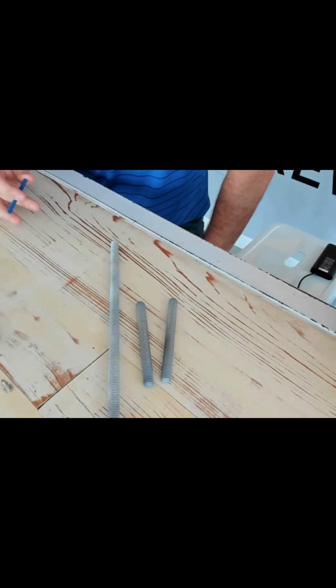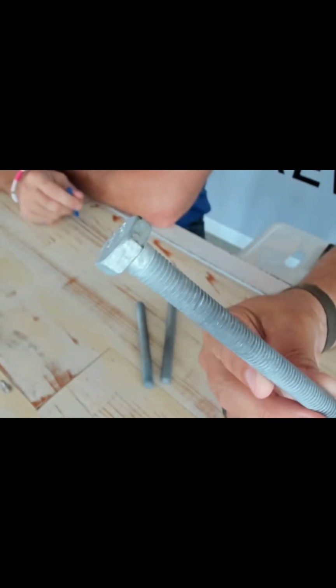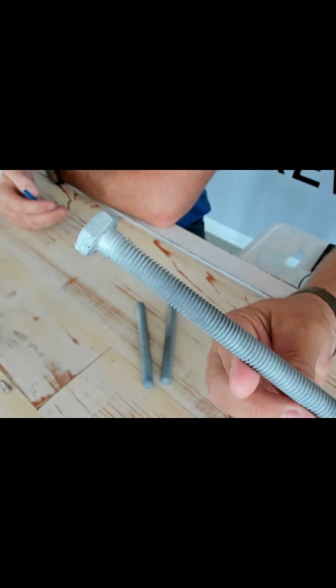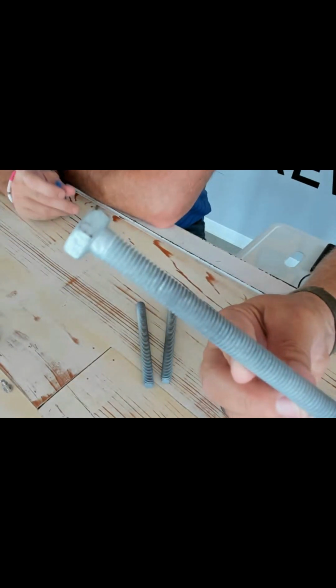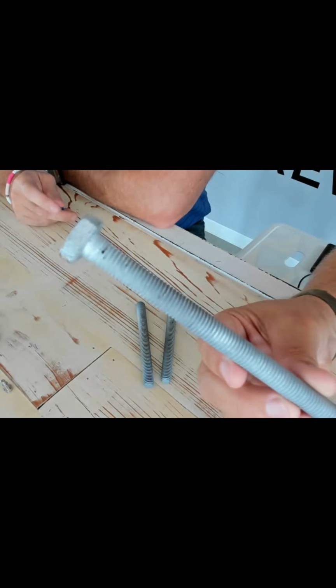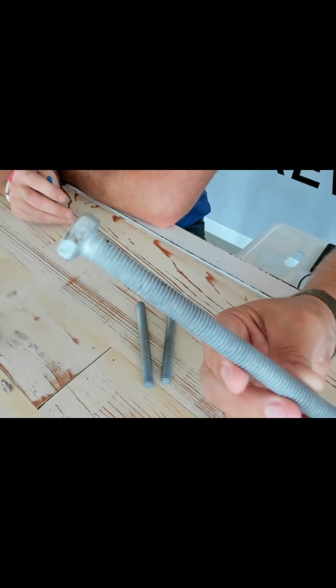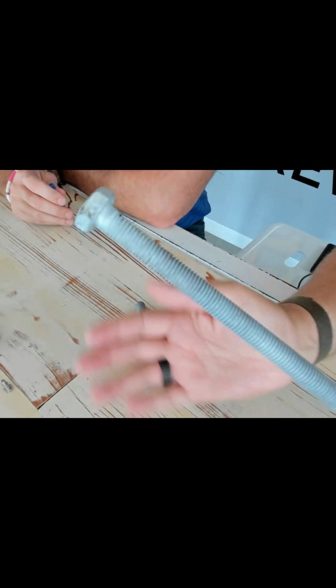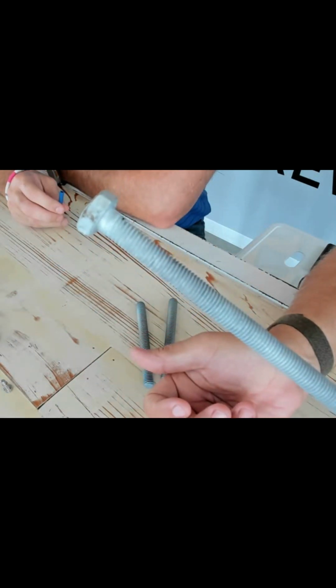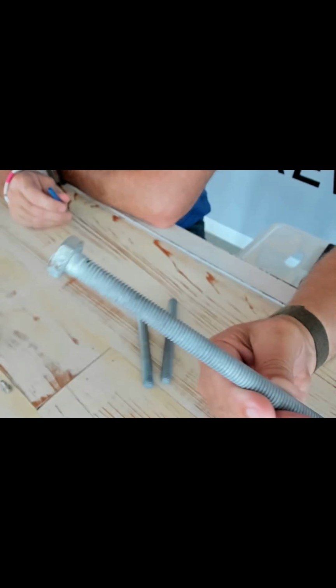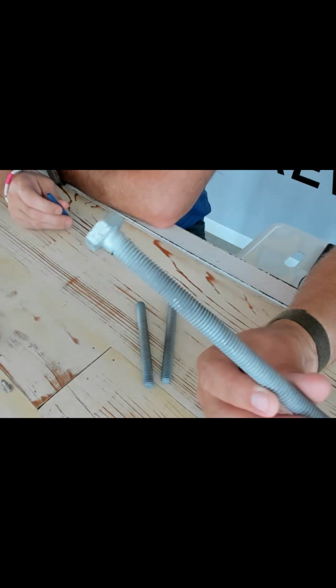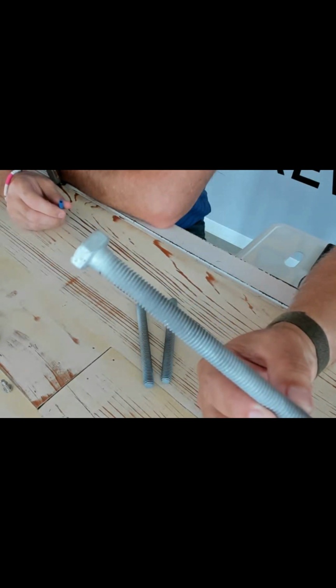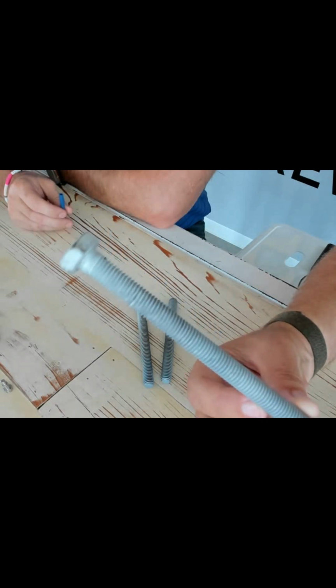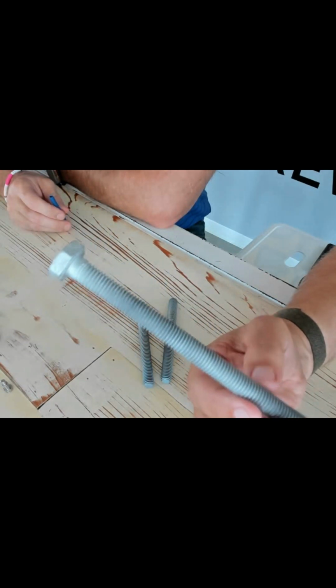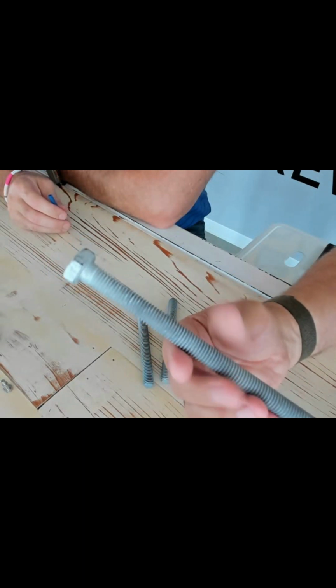Typically you see the hot dip galvanized in structural applications. So this is an A325 hex bolt, and typically they're not fully threaded, but I think this customer always wants them fully threaded. So this was brought in fully threaded, sent out to get coated. It's a very inconsistent coating because it is a dipping process. We talked about all these others being either electroplated, which is extremely consistent, or a spraying method, which again is operator specific. Whereas this one is very much a dip and almost a spin process where it's spinning and you're taking the excess material off. But what you're left with once it's dry is a fairly inconsistent coating and a very rough coating too.